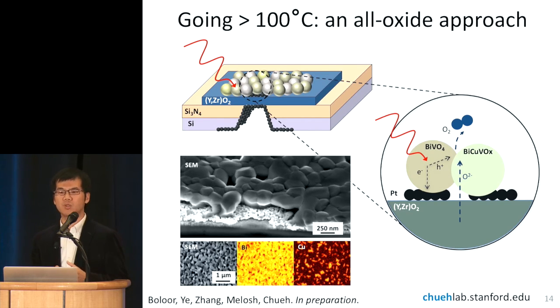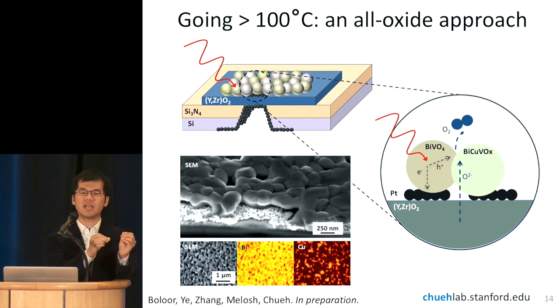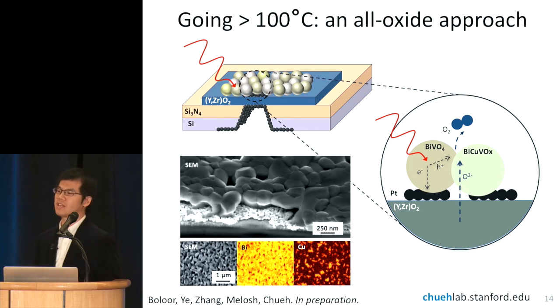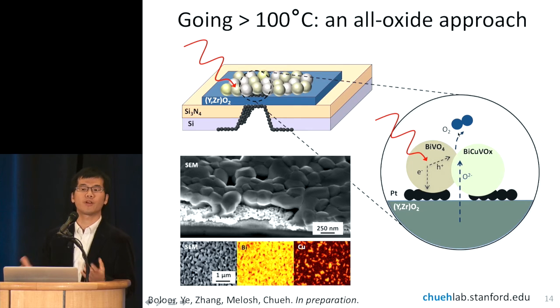What we have done here is we needed to add one more ionic conductor. So if you just put something like bismuth vanadate on zirconia, then only the intersection between the two will be active. That's where you can extract the photocarrier. But it will be good to surround the bismuth vanadate with something like water, something that can also help you transport the ions. And that's what we have done here. We added, in addition to the material that absorbs light, a material that also transports ions. And for this, we also use a bismuth-based material for compatibility. So we're using here bismuth copper vanadium oxide, which is an excellent ionic conductor.